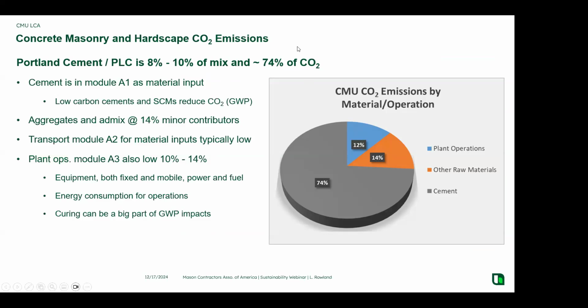You can see here that cement is a big part of the A1 emissions. Cement accounts for only 8 to 10% of the mix, but a full 74% plus or minus of all the CO2 associated with that. So cement is in the feed material to make a CMU, to make a mortar, or those kind of materials.